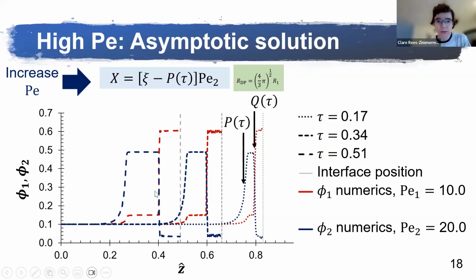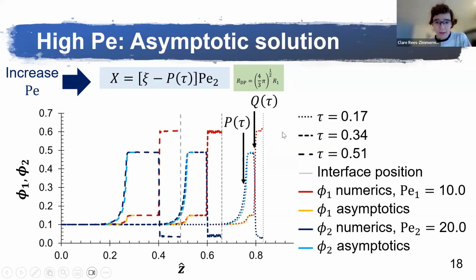I make a coordinate transform to a variable x, which is an expansion about P of tau. I then, in brief, solve for the concentration profile around P of tau and around Q of tau, and the values either side of Q of tau. In the lighter colors, I've shown the asymptotic solution, and you see that it's very close to the numerical solution. So it verifies the numerical code.